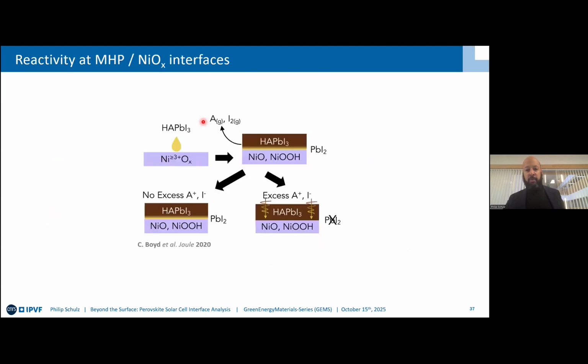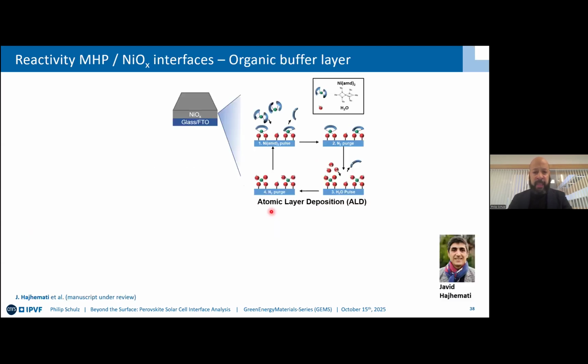Okay, so I close this part here with maybe a quick mention of nickel oxide being problematic if defective. And yes, we know this from this paper from Boyd, where they also went with the hypothesis of nickel oxyhydroxide species probed by XPS, and were able to see the formation of lead diiodide if you don't process your perovskite with excess A-site cations and halides in order to make a film without this PbI2 formation. Now, how is this, however, linked to the chemical reaction at the nickel oxide interface? It's not entirely clear.